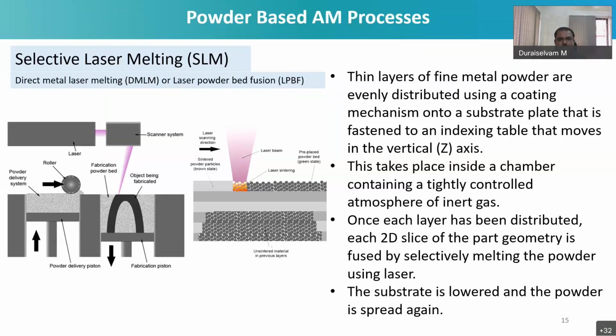metal-based product. And here, the thin layer of fine metal powder is evenly distributed using a coating mechanism onto the substrate plate that is fastened to an indexing table that moves in the vertical axis. So again, layer by layer deposition, move the powder bed down one layer at a time. Then finally you can realize the entire